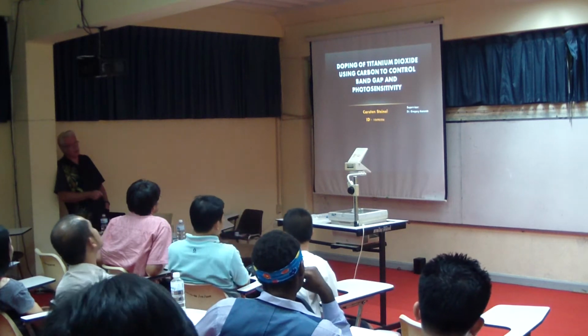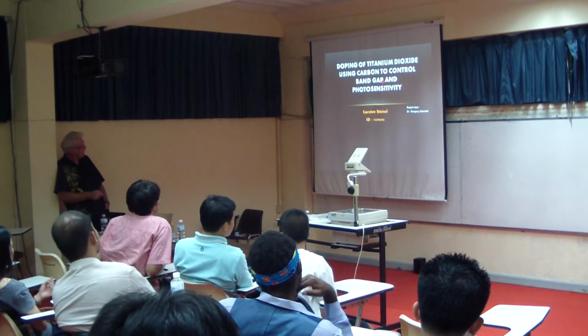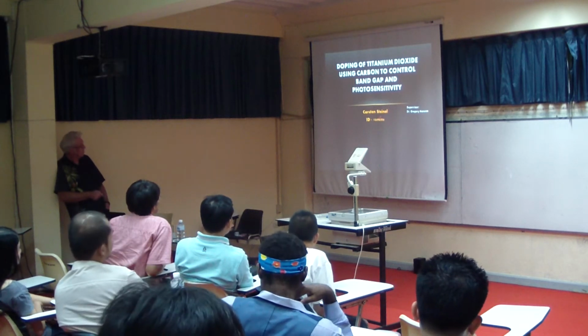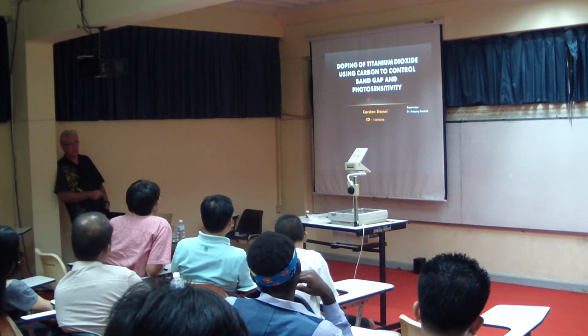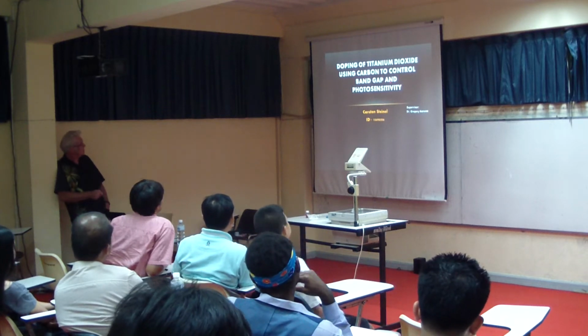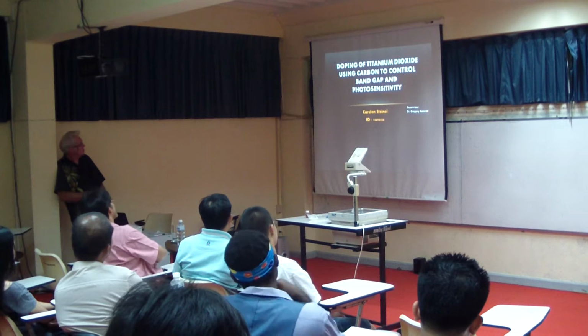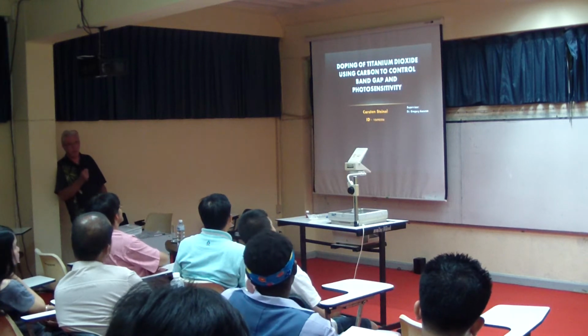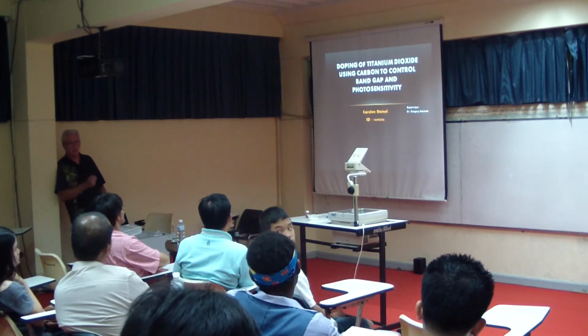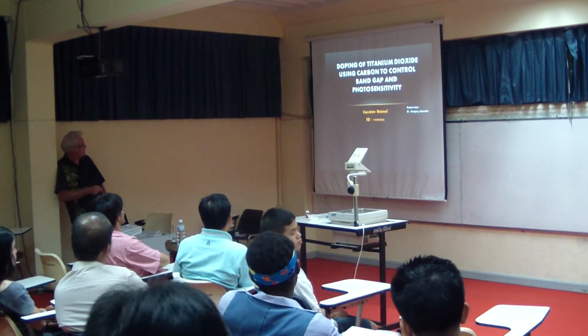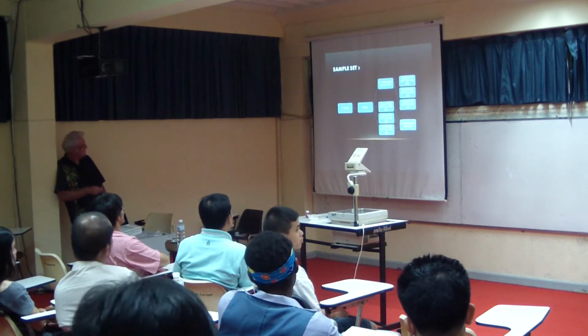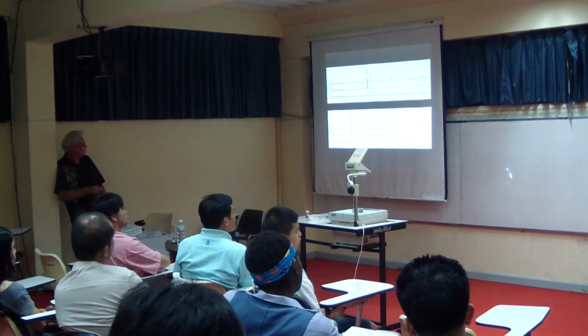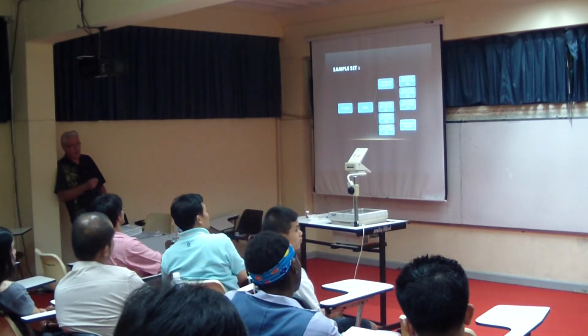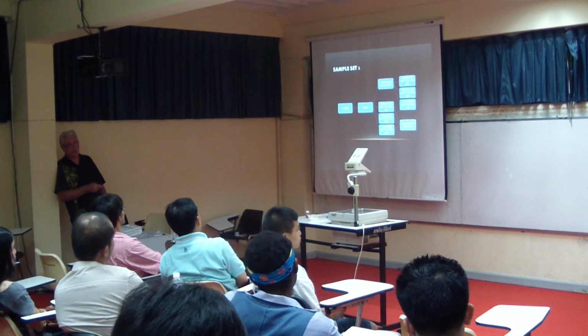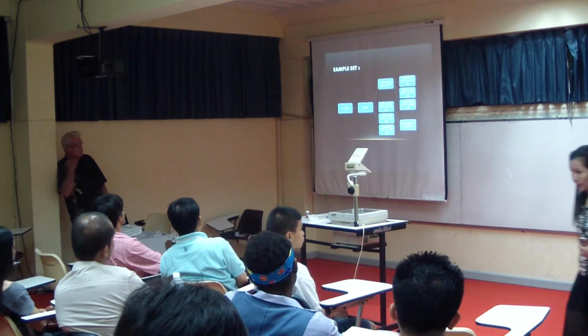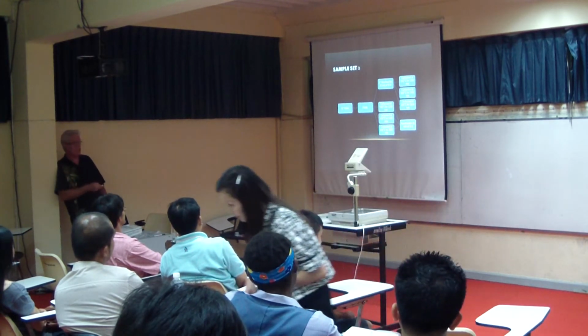producing photocatalytic materials. And this is my honours student last year, his honours with me. When we did this, titanium dioxide shows a lot of promise, however the band gap isn't quite right. So we looked at trying to change the band gap and get better photosensitivity. And we did that by simply diffusing carbon into the titanium dioxide. People looked at using noble metals. But we thought we'd use carbon.